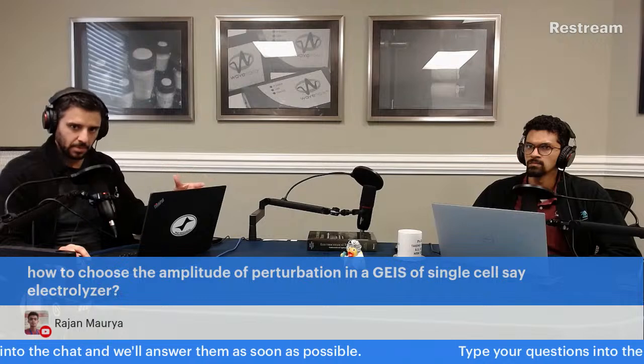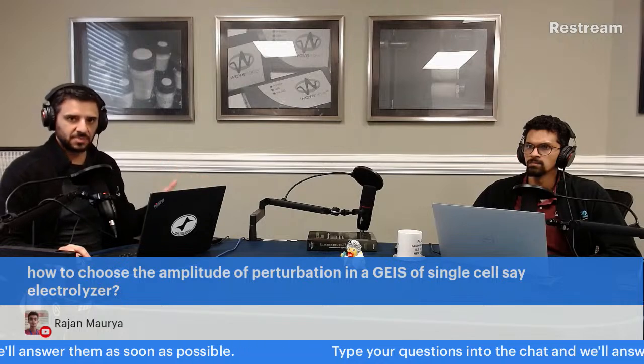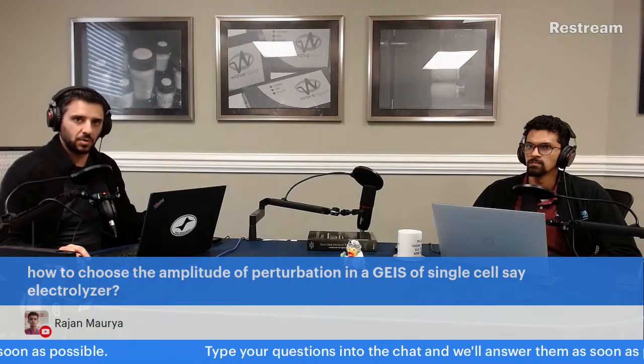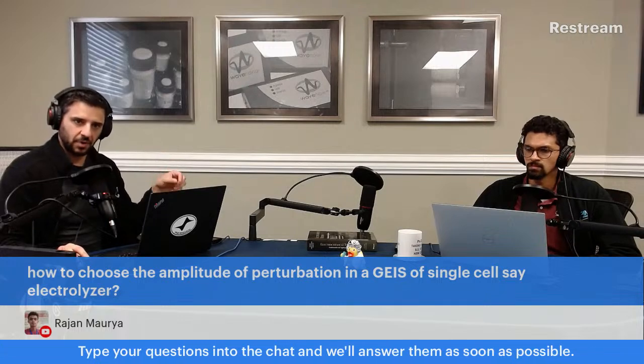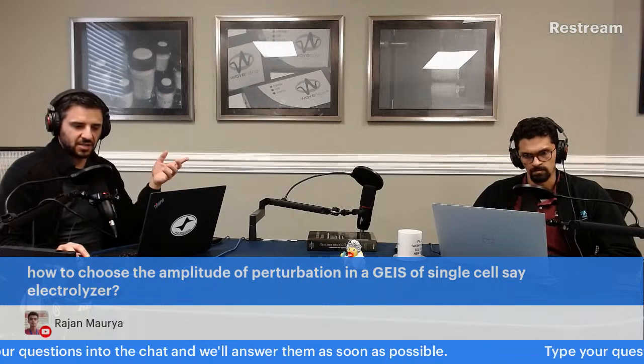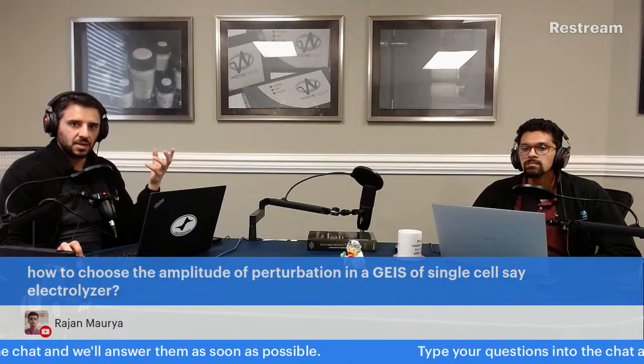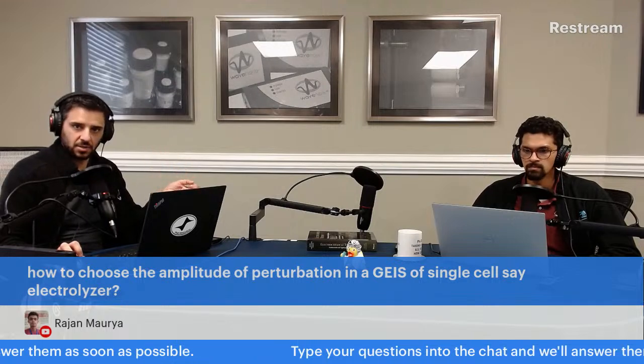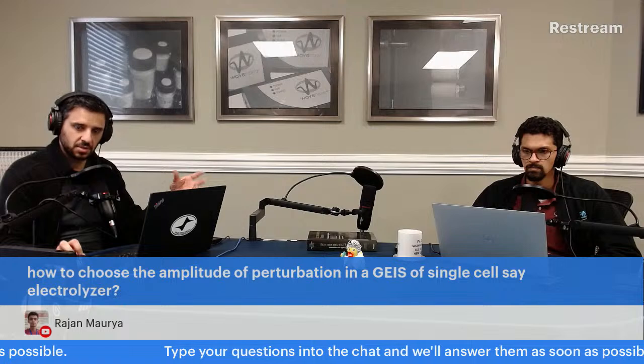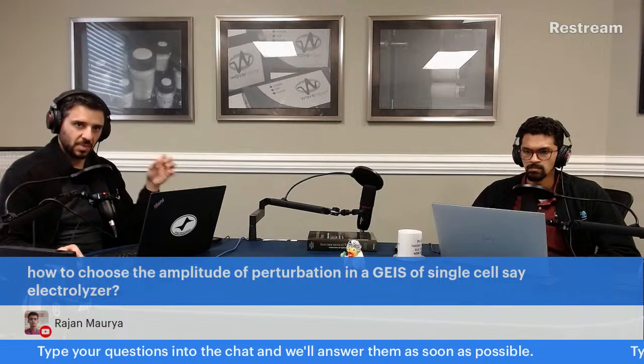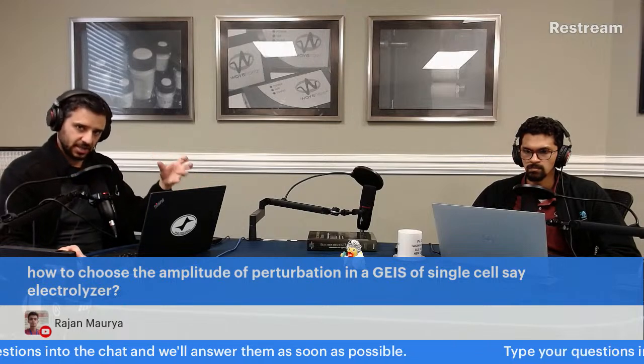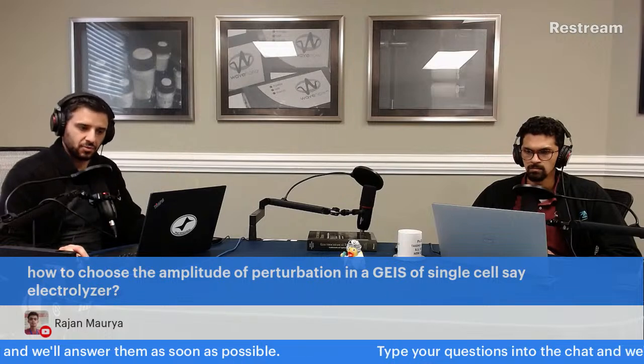Of course, it can be a problem if it's too large, but generally speaking, with galvanostatic mode, the problems are at high frequency. You get a lot of noise. So if you're looking for some decent data from like 1 kilohertz to 10 kilohertz or 100 kilohertz, and it's really noisy, you might need to increase your amplitude a little bit at a time to see if you can improve that.